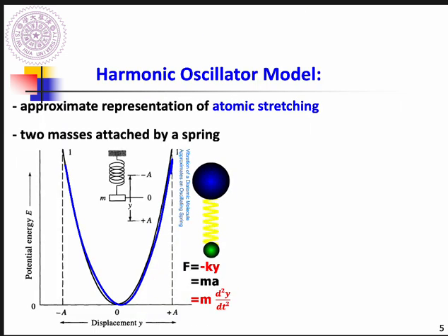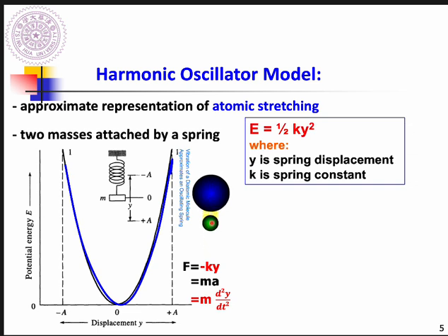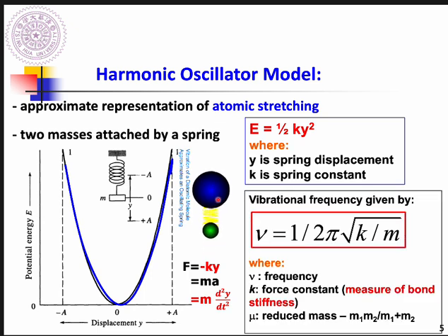Okay, so a quick review here. This is a harmonic oscillation model. The difference between this model and the classical one is that they do believe there are interactions between two atoms. This interaction is considered as a spring. So two atoms are attached by a spring, and we can use the spring constant to represent the interaction between two atoms. So this is more similar to the atoms inside crystal structures.